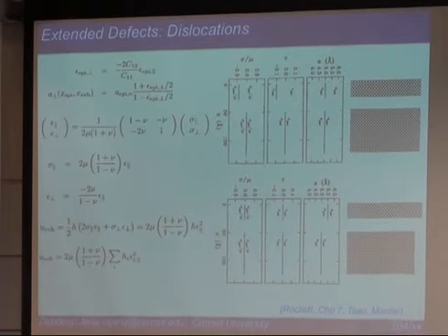That's what we mean by in-plane lattice matching. Whereas the perpendicular has become bigger. Does that make sense? I mean, you were at 5.5 to start with. In plane it became 5 angstrom because it had to strain this way, but because of Poisson ratio and volume conservation roughly, this lattice constant became longer, stretched out, right?